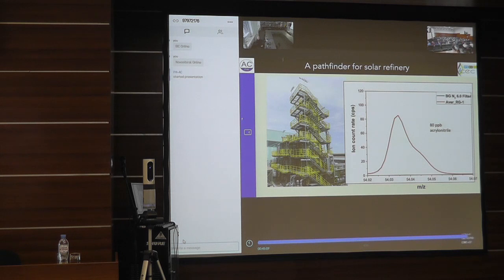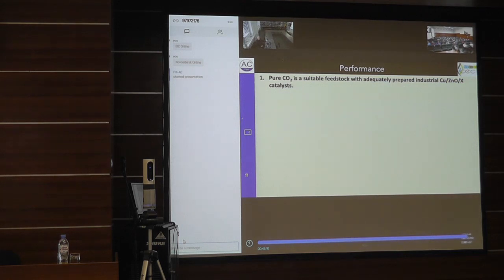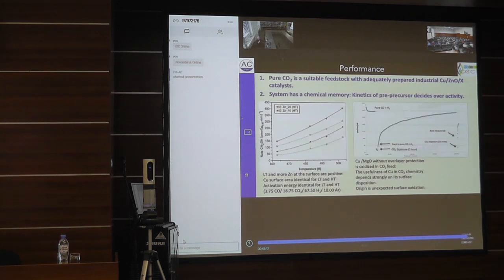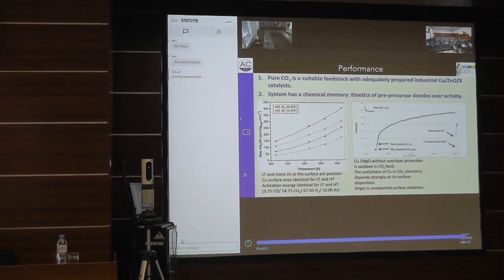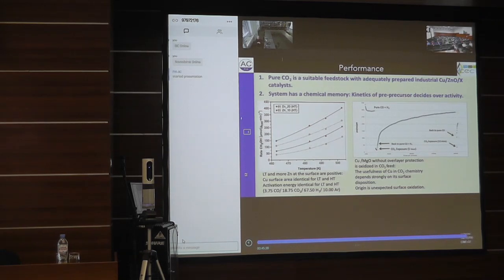Nevertheless, we have a good performance. You see here two important issues. If you want to modify the methanol synthesis between CO and CO2 as an input gas, you have to be careful because a copper zinc oxide catalyst that we use in this operation can only deal with CO2 containing gases. If you operate it only under CO with standard synthesis gas, this catalyst is immediately poisoned and then it recovers only after a very long time. And we studied this extensively.